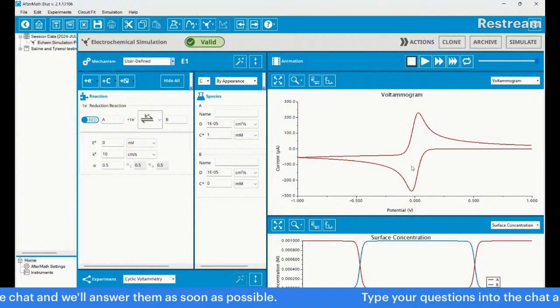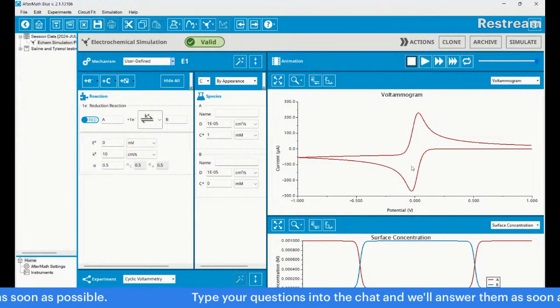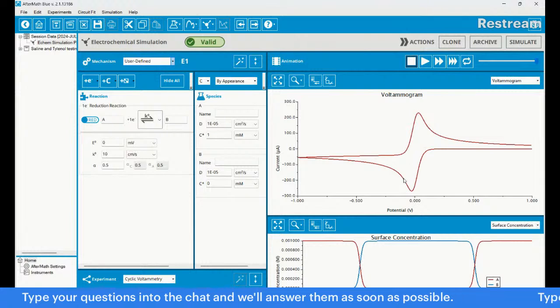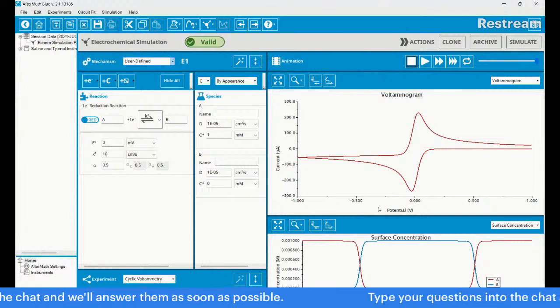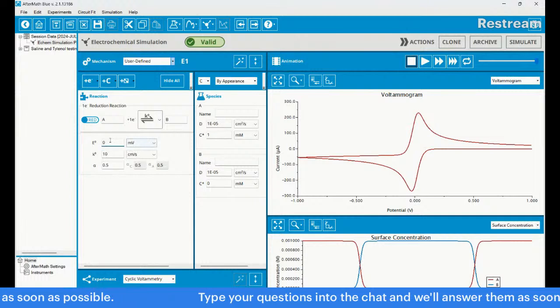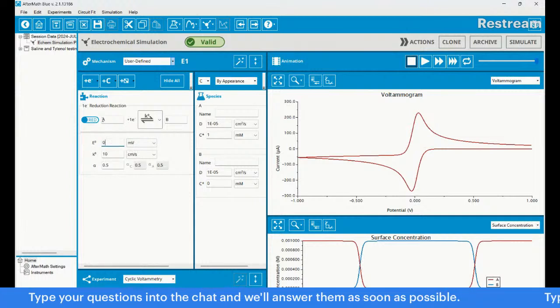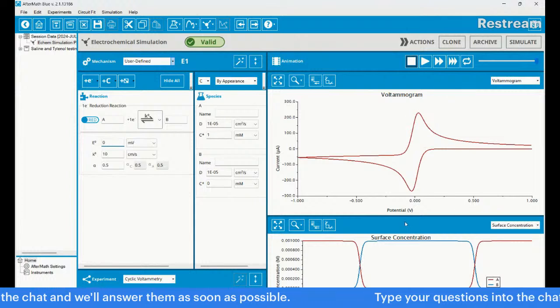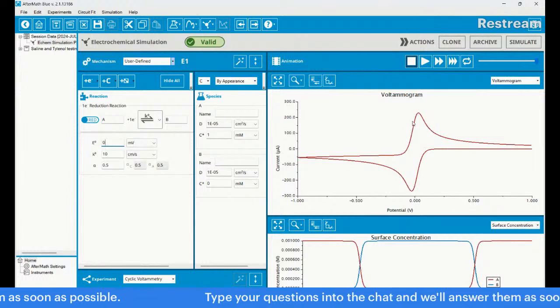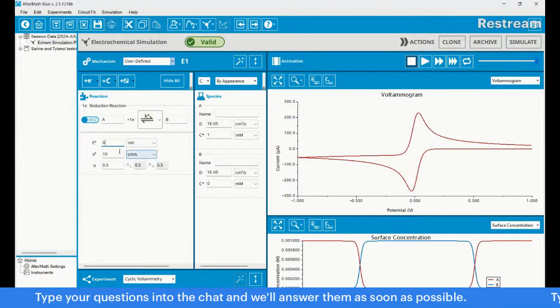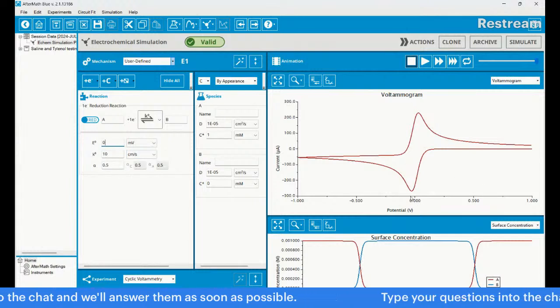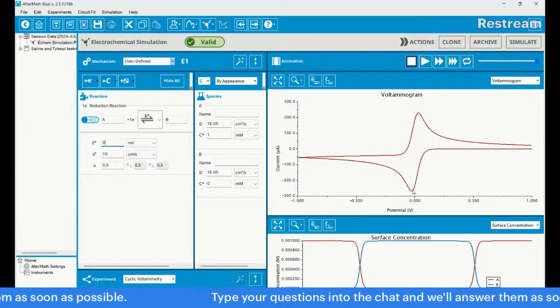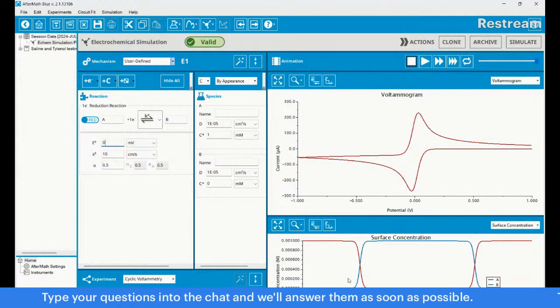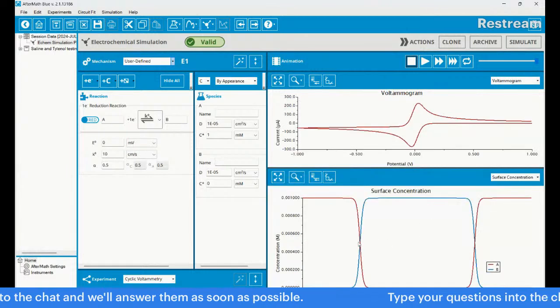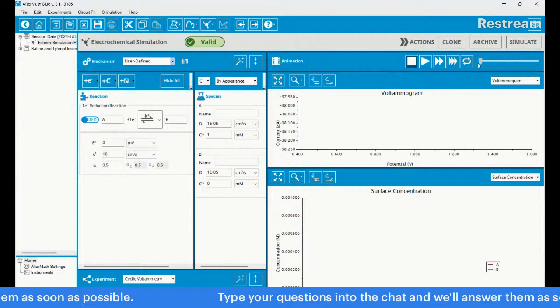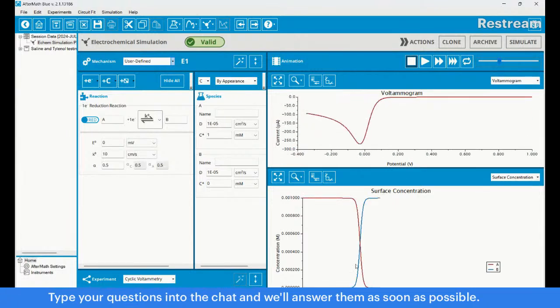So the potential, the E naught that you see in textbooks, at what potential does lithium or copper undergo an electron transfer or oxidize or something like that. That potential is this E naught that you can measure in the lab with cyclic voltammetry, and in this case, for a very fast electron transfer reaction, it represents the halfway point between this peak and this peak.